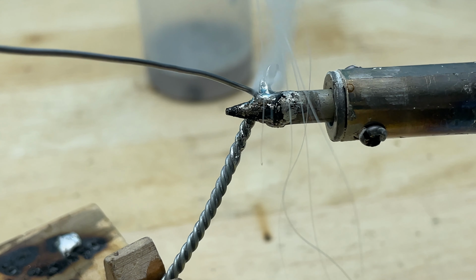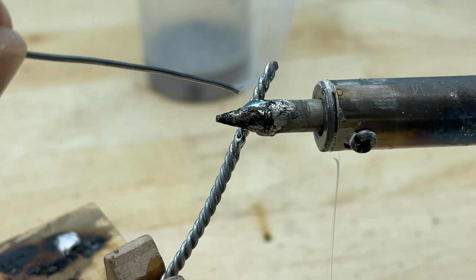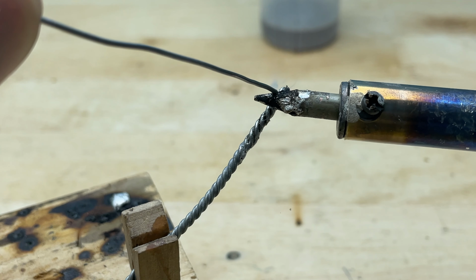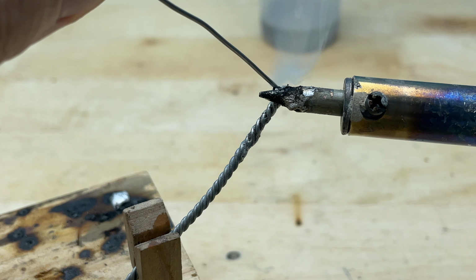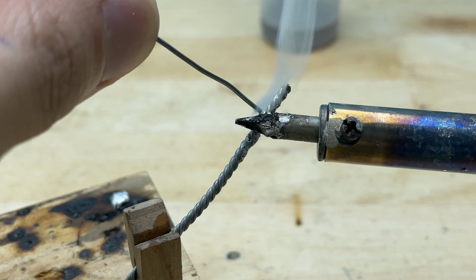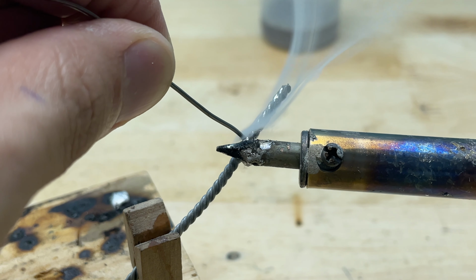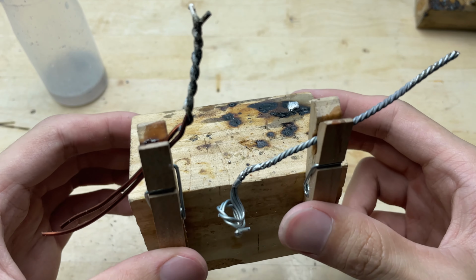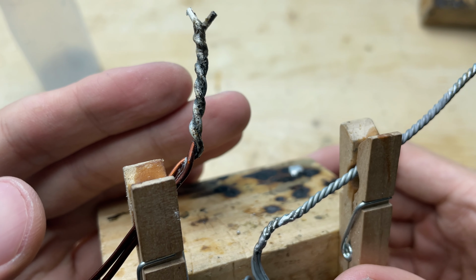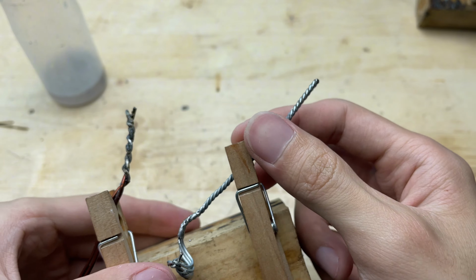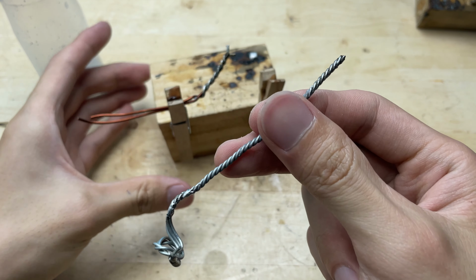The result is surprisingly clean and nearly perfect. The solder clings smoothly to the steel wires, forming a shiny, uniform joint without lumps or gaps. It looks professionally done, solid, neat, and durable. This shows that even with basic materials, a well-prepared flux solution can produce high-quality, reliable solder joints.